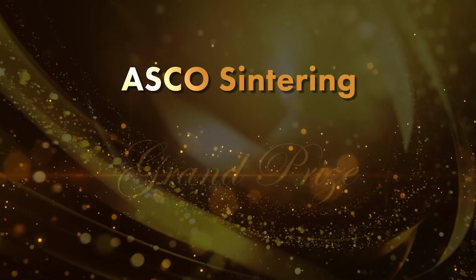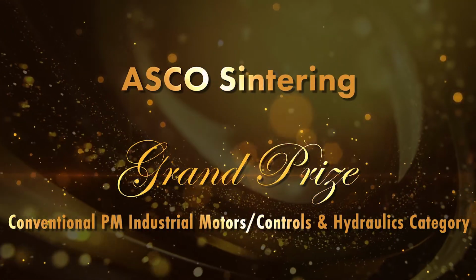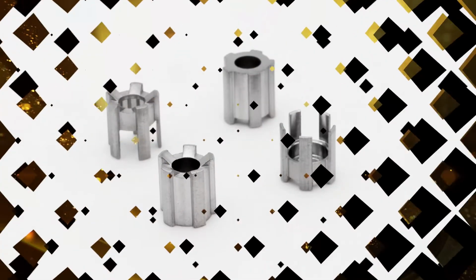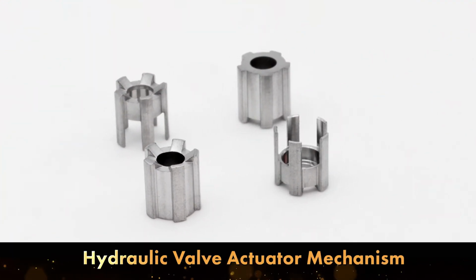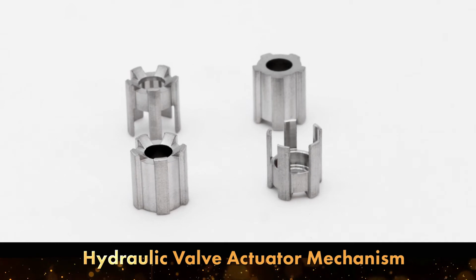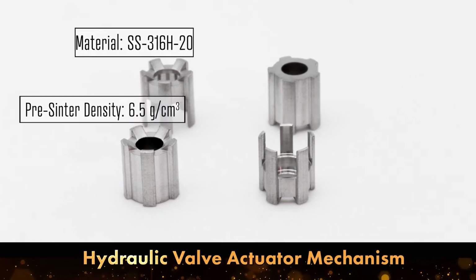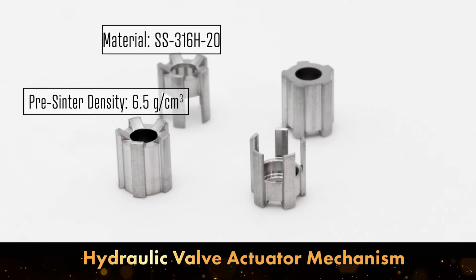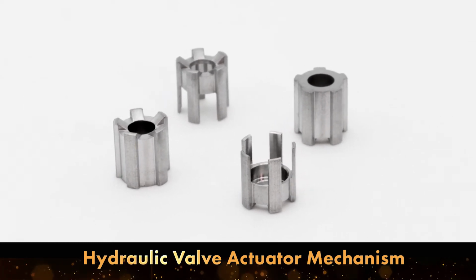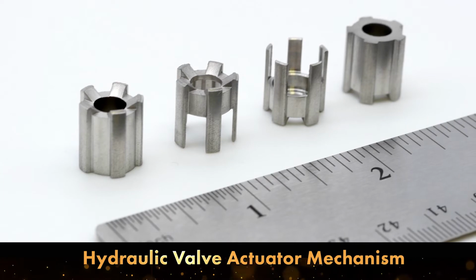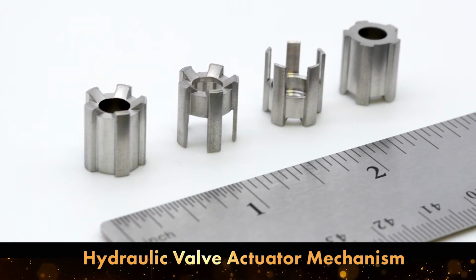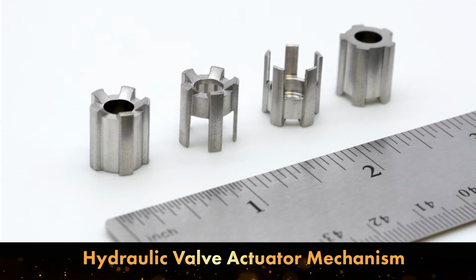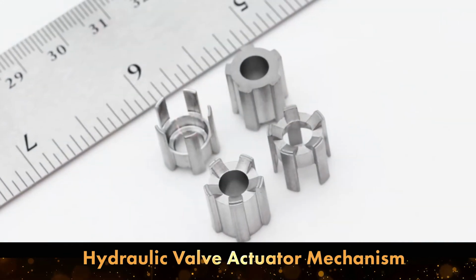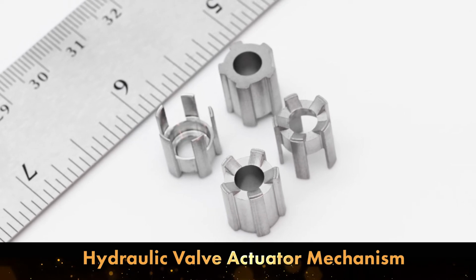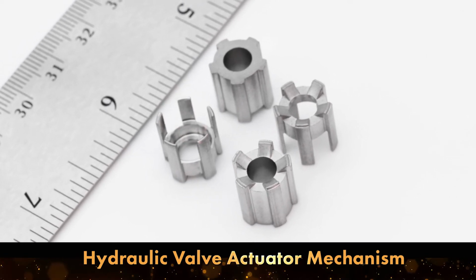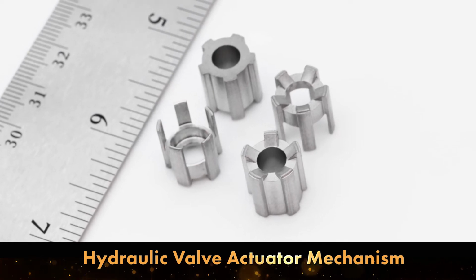ASCO Sintering has won a grand prize in the Industrial Motors, Controls and Hydraulics category for PM components. This award-winning component is the spring seat of a hydraulic valve actuator mechanism. The part is made from 316H-20 stainless steel and is compacted to a green density of 6.5 grams per cubic centimeter prior to sintering at 2100 degrees Fahrenheit in a pure hydrogen atmosphere. The sintered parts have a density of 6.6 grams per cubic centimeter, and the nitrogen content is kept below 0.03% weight to ensure good ductility for the part and the durability required for the cyclical loading of the hydraulic actuator.